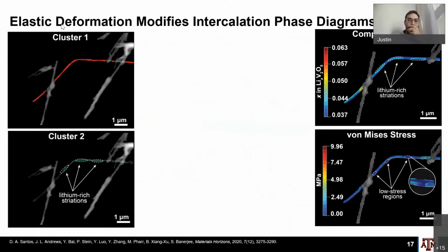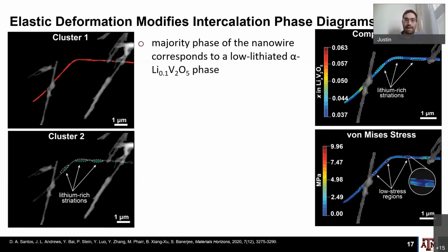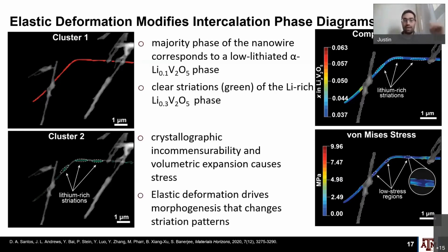So, going back a little bit, we have recently started looking statistically at these materials. The way that these V2O5 nanowires fall within these matrices and cathodes is that they have inherent bends or defects. As we look at composition maps, we found that the curvature within the materials, and in turn the strain, dramatically affects the way these things lithiate and the way the phases orient with respect to each other.